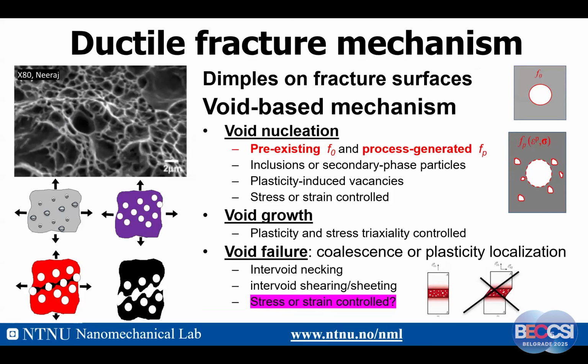Okay, let's look at ductile fracture. That's my talk. Ductile fracture is a field which is massive. Everyone has heard about this. There are a lot of studies already carried out. For the ductile fracture mechanism, if you look at the fracture surface, there are a lot of dimples. So we have three stages of ductile fracture. We have void nucleation, from the particles, through particle fracture or particle debonding from the matrix. This nucleation could be stress or strain controlled. We could have plasticity-induced vacancies that could nucleate voids. This is very exciting for hydrogen embrittlement, which we are working on now.